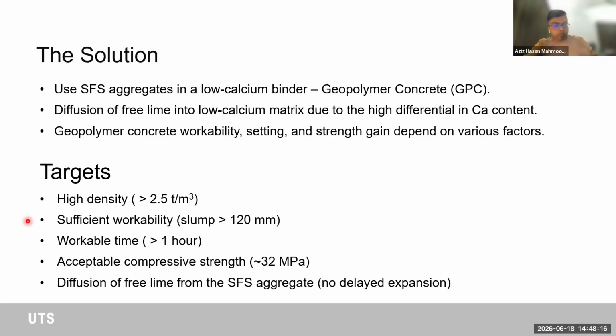If anyone within the audience is from a concrete background, you know that workability is an important aspect of concrete delivery and supply and placement as well. We're trying to have a workable time of over 1 hour, taking into consideration for the concrete trucks to come from the plant onto the site, and also pouring and compacting the concrete. The compressive strength is not a critical factor here. The most critical factor is the high density, but we're targeting 32 MPa of compressive strength, so we can move around the high density armor units from the site onto the breakwater. And also we're targeting the diffusion of free lime from the steel furnace slag aggregate into the concrete mix.